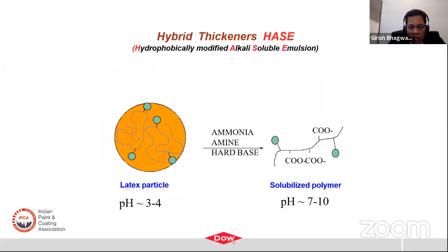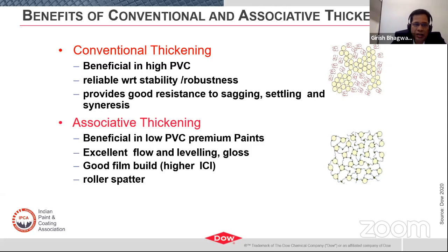And there was a need for developing a hybrid of both technologies. So that's how HASE thickeners appeared on the scene, which use the mechanism of associative thickening and the conventional thickening, right? So it's a two-in-one kind of thickener. It enables you to achieve high to mid PVC paint viscosity so that you can allow the paints to be diluted, and at the same time it allows you to have that associative network which will enable you to have a film which is more uniform when you eventually apply it. Now we have actually done the testing in our lab to see the effect of this. Okay, before going there, let me talk of the benefits of conventional thickening and benefits of associative thickening.